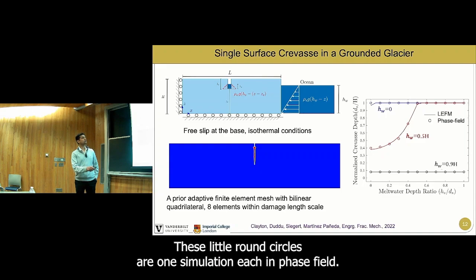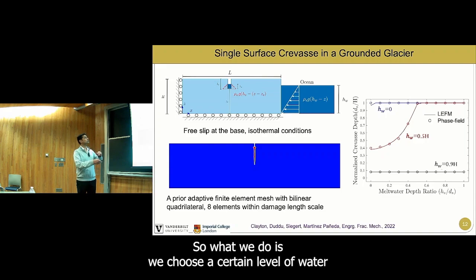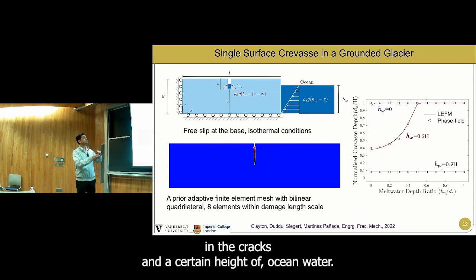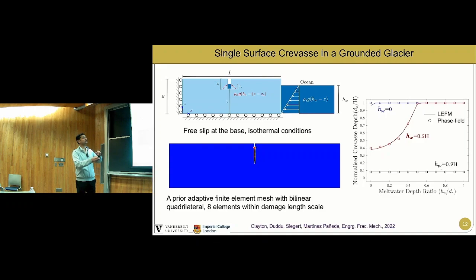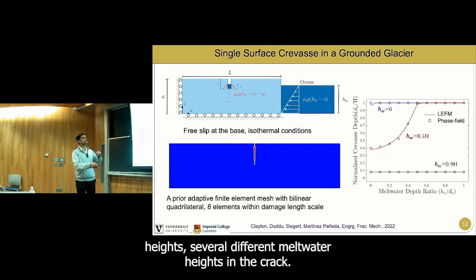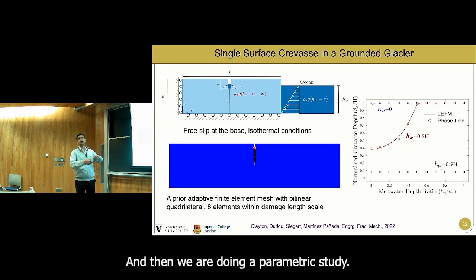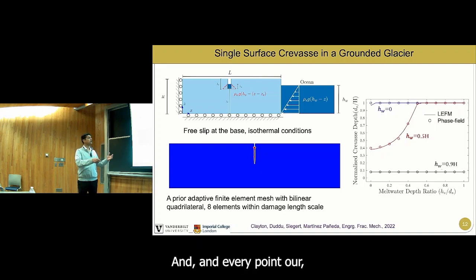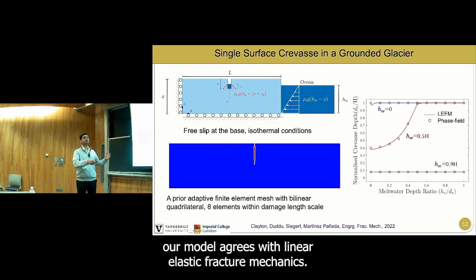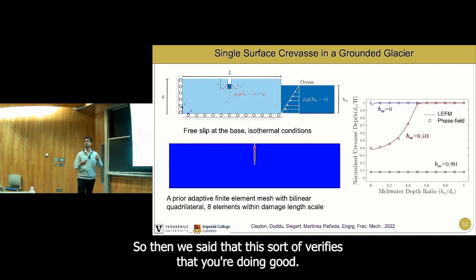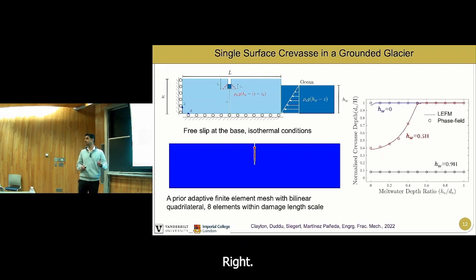These little round circles are one simulation each in phase field. So what we do is we choose a certain level of water in the cracks and a certain height of ocean water. And so we have 3 ocean water heights, several different meltwater heights in the crack. And then we are doing a parametric study. And every point our phase field model agrees with linear elastic fracture mechanics. So then we said that this sort of verifies that we are doing good, right?